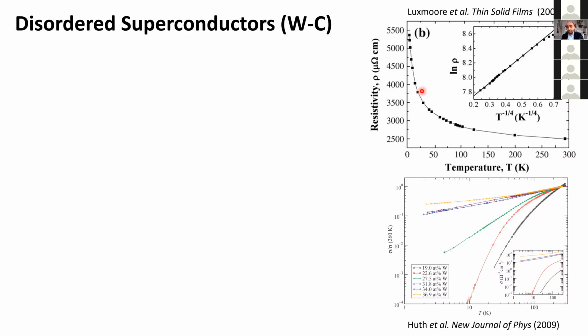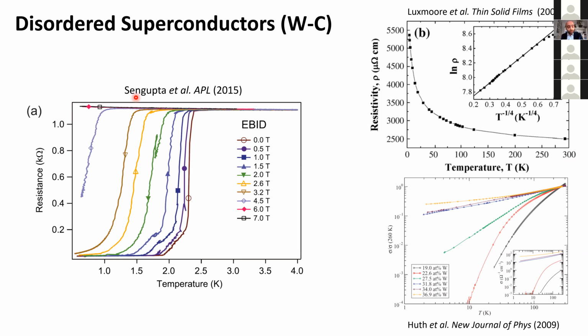And there were no reports of a superconducting transition even. Most of these structures just turned out to be insulating, let's say, until 2015, where a group finally succeeded in making superconducting tungsten carbide with this technique, but the transition temperature was about, I think, 2 Kelvin. And this, well, kind of became widely accepted as the limit of what this EBID can provide.